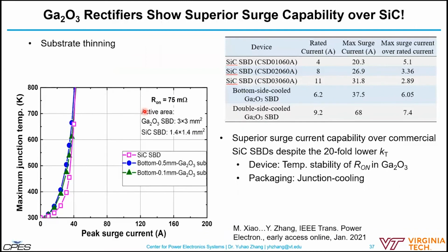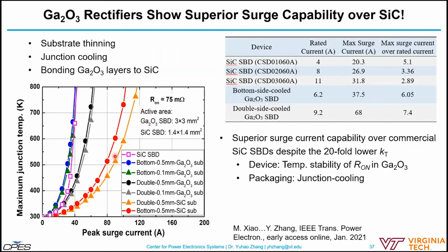So in that regard, the thermal resistance of the upwards path will matter. That's why if we change to a silicon carbide substrate, this shows the bottom and the double cooling. The bottom cooling means that all the heat has to be extracted through the silicon carbide substrate. In this regard, it shows that if we can transfer to the silicon carbide substrate, even with just the bottom cooling, it can provide a pretty good surge current capability.